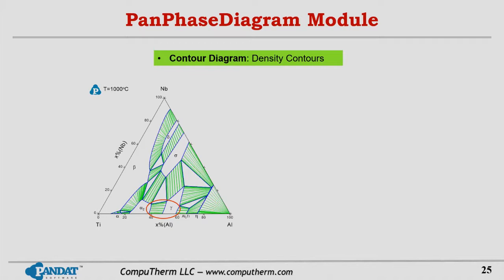Titanium aluminide alloy design: the main feature of titanium aluminide is that it's lightweight, and the composition in the middle is basically around 50% titanium and 50% aluminum. However, niobium is one of the important additions to titanium aluminide. The question is, in order to reach certain properties while keeping the alloy light, how much niobium can we add? We do not know from this phase diagram only.